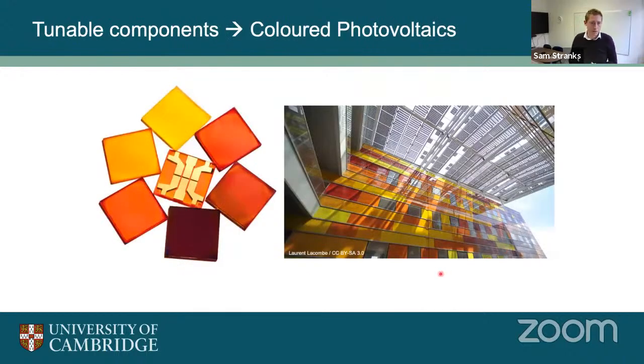We can also change the properties and tune the composition, so we tweak the composition of these materials, and we can actually change the color that they absorb or that they emit. And so this is an example of if we have a pure iodide, if we think about the halides. If you remember, I talked about one of the components being a halide. This is the iodide, and if we mix in a little bit of bromide, we can actually change the color all the way around to, for example, this yellow, which is a pure bromide system. And this opens up applications in colored photovoltaics, for example, so we can integrate these into buildings and actually design them into the facades of buildings. And there's a growing area of this building integrated PV where this can be very applicable.